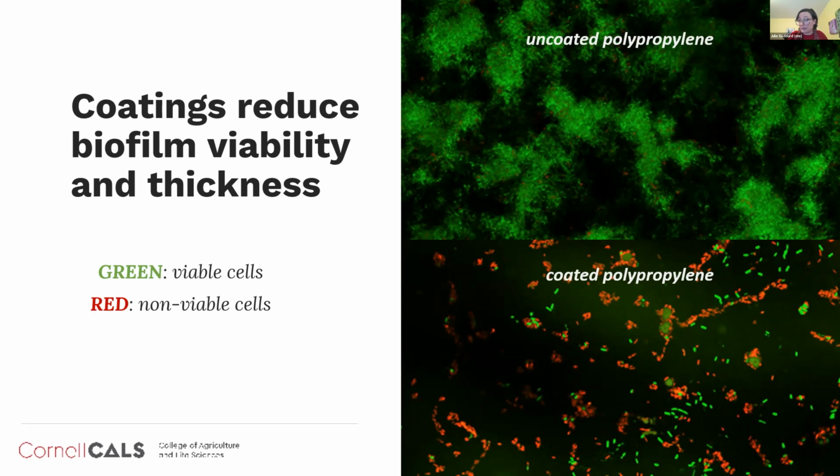So this is a big finding, right? Because it shows our hypothesis from earlier might hold some water, that even your best antimicrobial non-fouling material, given enough exposure to a good, nutritious environment, will result in bacterial adhesion and potentially biofilm formation. So if those adherent cells could be largely non-viable, that's really good.